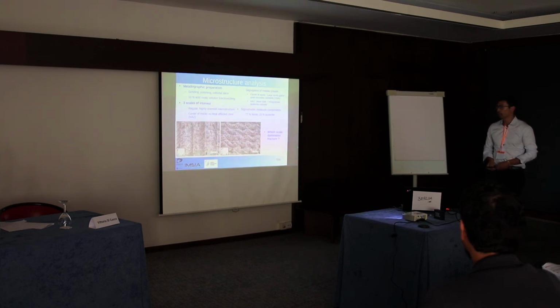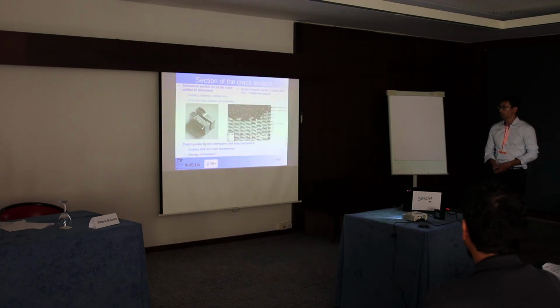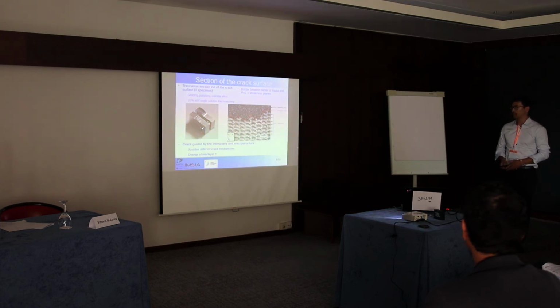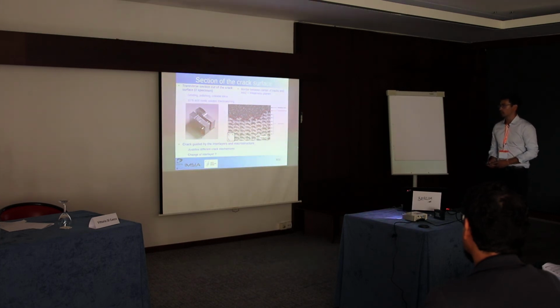So now the question that arises is, among these scales, which is the one that dominates the crack growth? There are at least two of them that come to mind. First, there is the mesostructure with the printed tracks, and the second one is the scale of the phases. As a reminder, we have said that the ferrite is more brittle than the austenite. So to answer this question, we have performed a cut of the crack surface here, as illustrated by the white dotted line. And following the same preparation as before, we can reveal where the crack passes through in the microstructure.